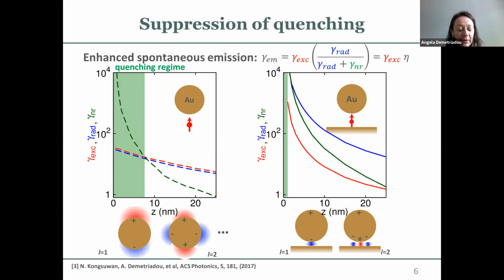Just to give you a bit of an insight, when I'm saying excitation rate, what do I mean? I mean that I have a plane wave incident on my system, and I'm measuring, where I'm planning to put the quantum emitter, the field enhancement, because that's how strongly my quantum emitter will be excited. While for the radiative decay rate, I'm putting a quantum emitter, a dipole, and when it emits a photon, I'm detecting in the far field how much of that energy from the quantum emitter reaches the far field. So it makes sense that for the isolated nanoparticle, the excitation rate and the radiative decay will be the same because of reciprocity, but I would expect something similar to happen for the nanoparticle on mirror, but it does not.